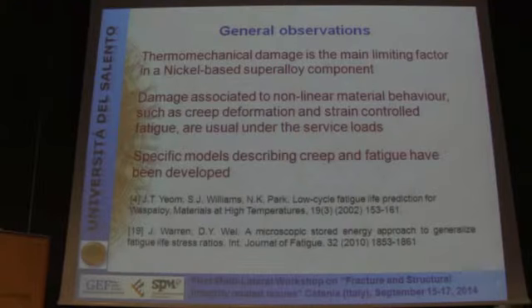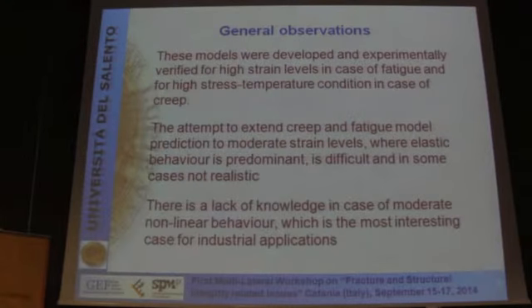A lot of models exist in literature to describe this damage mechanism, and these are some examples. But all these models have a limitation: they are developed and experimentally verified only for high strain levels in the case of fatigue and for high stress and temperature conditions in the case of creep. So if we try to extend the prediction of these models, we obtain unrealistic predictions, or in some cases it is very difficult.